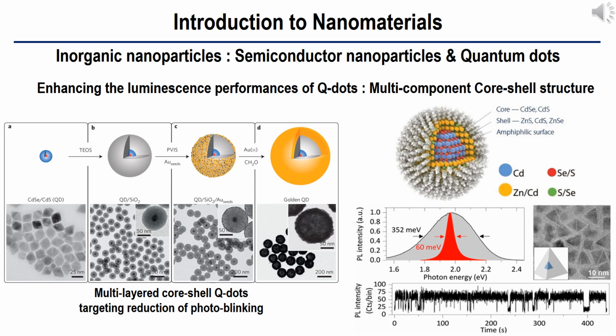We can modify the crystal structures or shapes of quantum dots to enhance quantum efficiency and suppress photo-blinking. As shown in the lower right figure, pyramidal-shaped quantum dots exhibit very narrow peak width for the fluorescence as well as suppressed blinking. It is also possible to use a mixture of the multi-components without the core shell structures. Due to chemical potential gradient, it is possible to drive the microphase separation in the quantum dots, in which large bandgap materials can be driven to form the shell-like structure. However, every component is distributed over the quantum dots. Another way is to use silica sheath and metallic nanoparticles on the sheath. As shown in the left figure, this configuration shows good quantum efficiency and suppressed photoblinking.